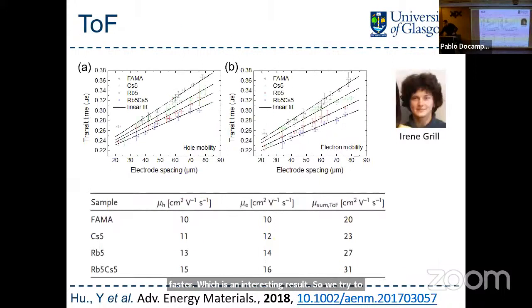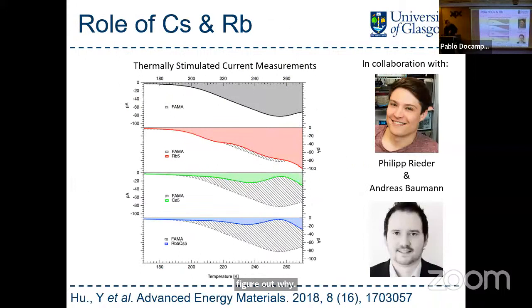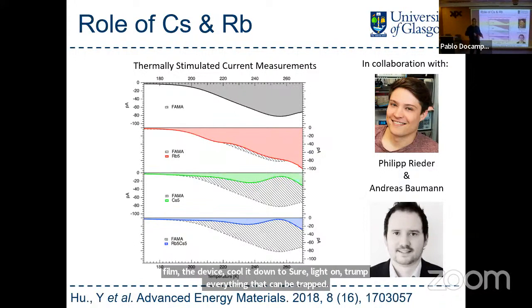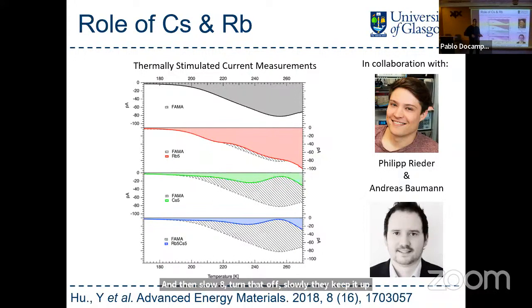We also did this one, which is not that interesting. This one's the more interesting one. One of the measures you can do is you can take your film, your device, cool it down to liquid helium, shine a light on it, trap everything that can be trapped, and then slowly turn the light off, slowly heat it up and see how many charges come out at what temperature. That gives you an idea of how deep those traps were to begin with.